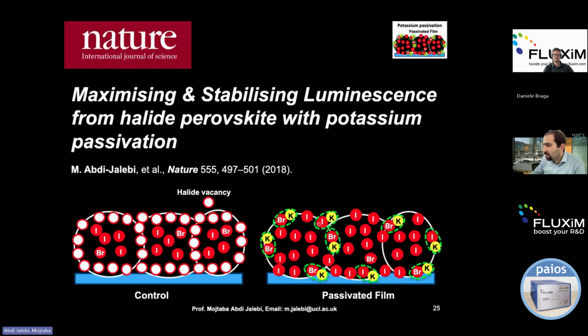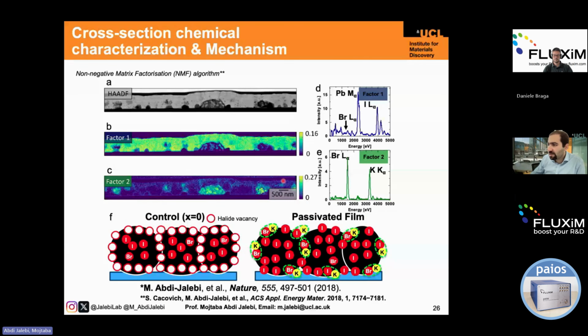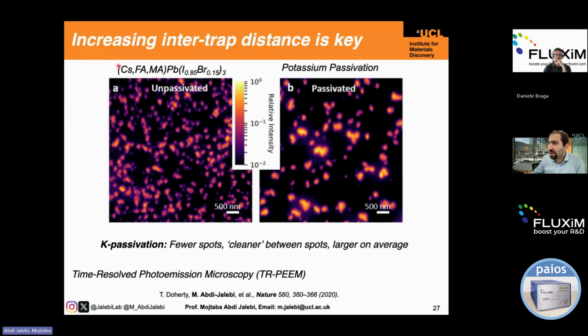The other innovation here is to have potassium there. Potassium helps us block or lock the extra ions at the boundaries. Specifically, they bind with bromide and lock it up at the grain boundaries. On the other hand, it also prevents these ions from moving, which is another big problem in perovskite. To confirm this proposed mechanism, we did cross-sectional TEM that shows we are actually forming this potassium and bromide phase, which is also rich at the grain boundaries and interfaces. And in a follow-up work we utilized time-resolved photoemission microscopy to locate the defects in the semiconductor.